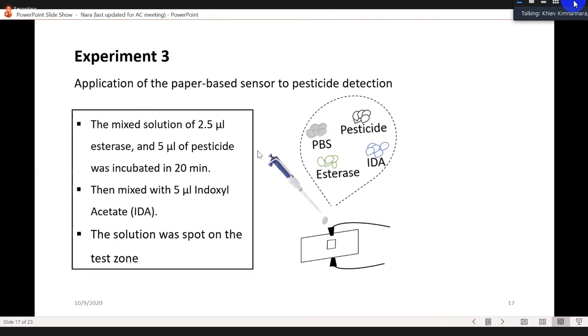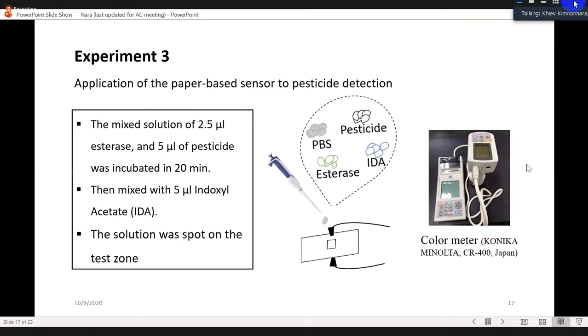In order to apply my system for pesticide detection, first, a mixed solution of 2.5 microliters of esterase and 5 microliters of pesticide was incubated for 20 minutes. After that, it was mixed with 5 microliters of indoxyl acetate. Then the solution was spotted on the test zone here, and I applied the heating system like this. After that, a colorimeter was used to measure the color changes after the enzymatic reaction happened.